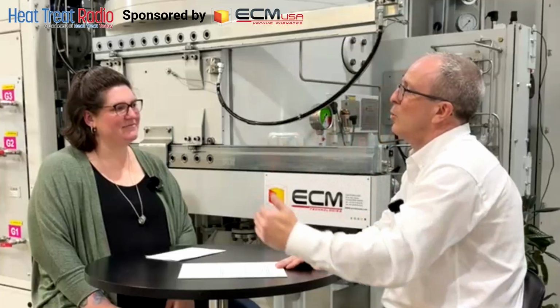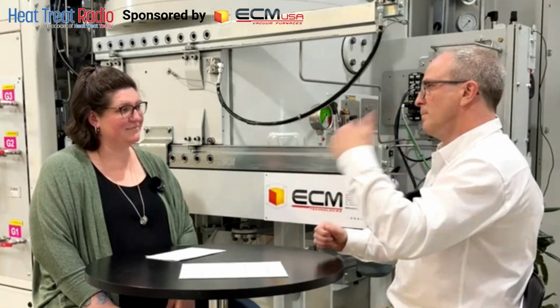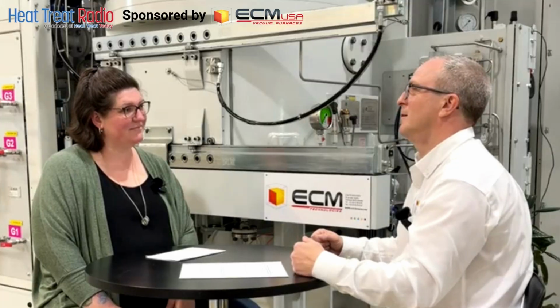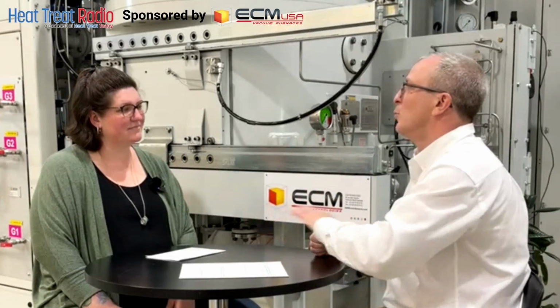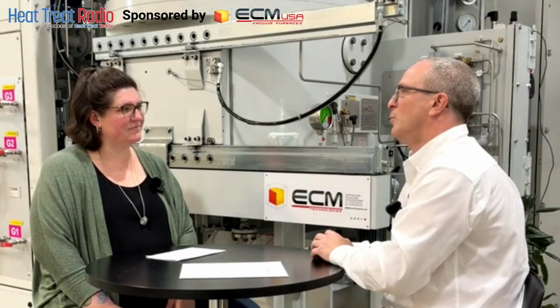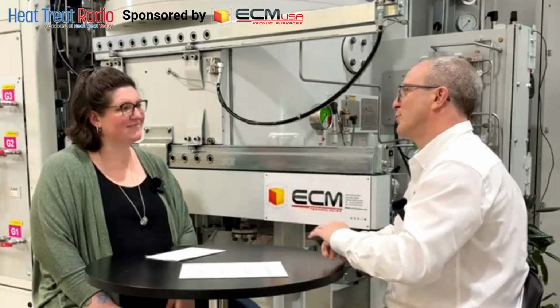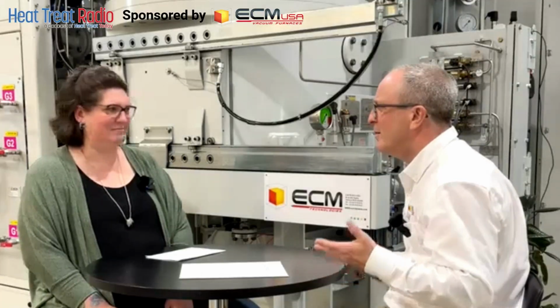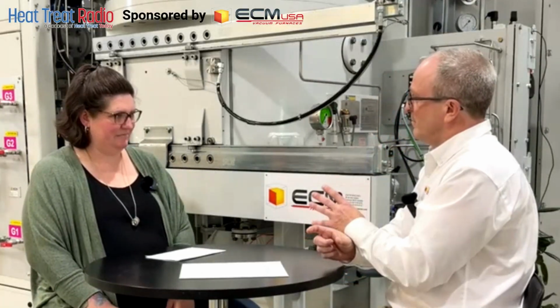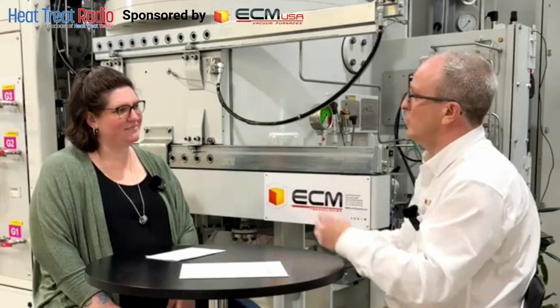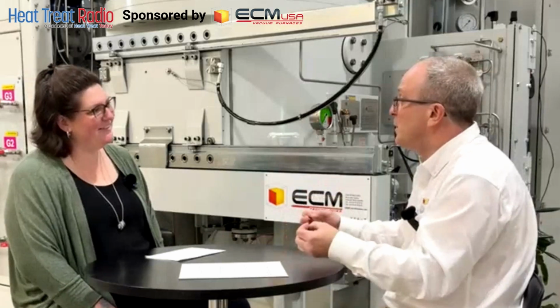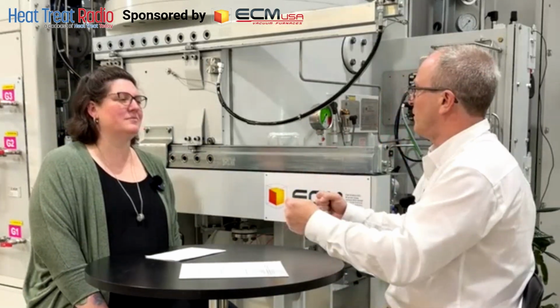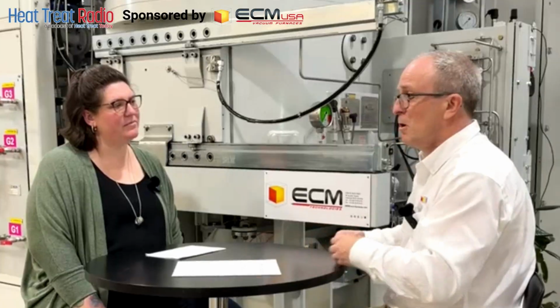You need to always look at the curves. And today, if you have an issue of temperature out of the range, you will have an alarm. So constantly you can check if it's good or not without checking the metallurgy. If you treat a big part, usually you don't cut the part. Because if you have 6 parts in a load or 10, no, you have samples. So you have to validate primarily your sample and your real part at the beginning. Make sure it's representative. Exactly. Or if there is a difference because you cannot find exactly the same material, you know the difference. And the difference would always be the same. Right. Make it predictable. Yes.